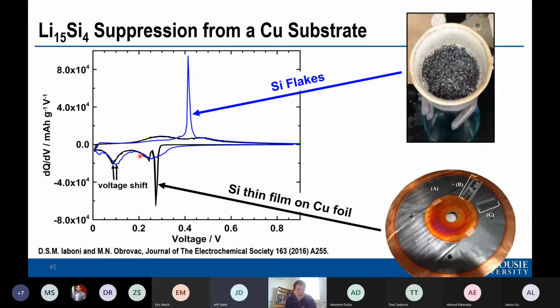And you could see during lithiation, there's a little peak here, and that's the instantaneous lithiation of 15-4, or crystallization. And during delithiation, you see the big two-phase region here from the delithiation of the 15-4 phase. If we kept the amorphous silicon on the foil, then you get this black curve. And the first interesting thing is you see this big peak here. This peak is a nucleation and growth peak.